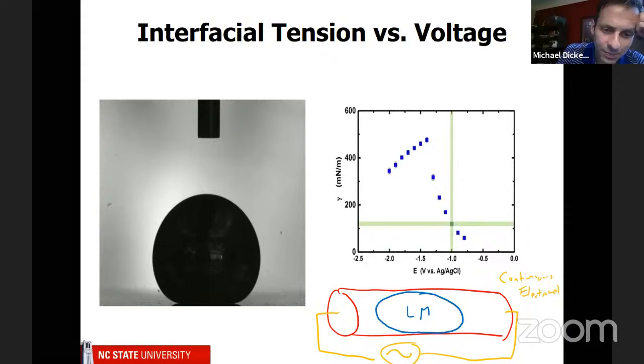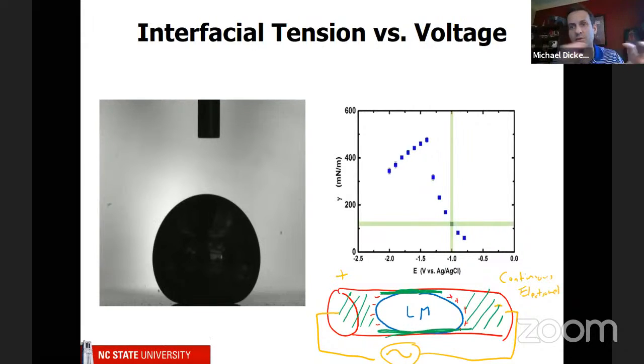The basic idea is that when you apply, let's just say positive voltage here and negative voltage here, then, let's see, I have to remember that's positive. I think that becomes negative at this surface, and this becomes positive at this surface. And so as a result, you get a gradient in surface tension that causes the metal to move back and forth. And that works very well. That is a good way to move the metal. I probably should have shown that because this is pretty simple and easy to do. One of the reasons it works is that the electrolyte, everything else that you see in here, is all water. There's a little thin layer that seems to form between the liquid metal and the walls, and that makes it so it doesn't stick. So it allows it to slip. Anyway, that's one thing that people have done with AC that comes to mind.